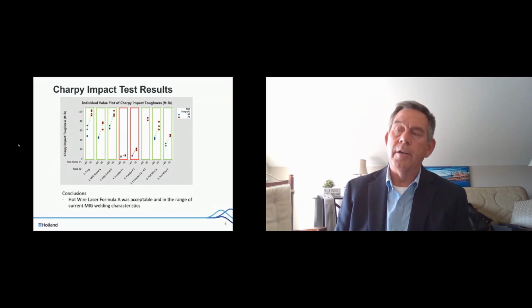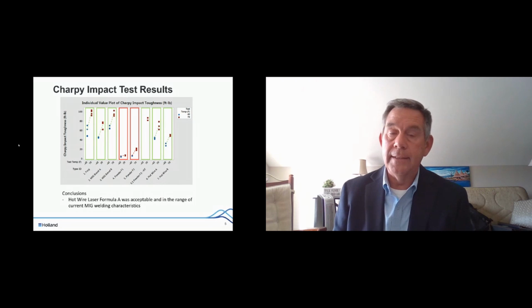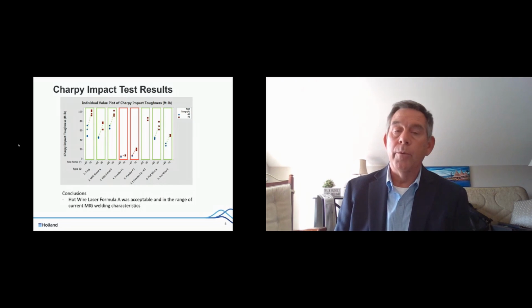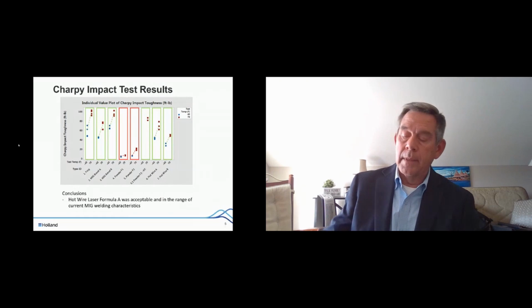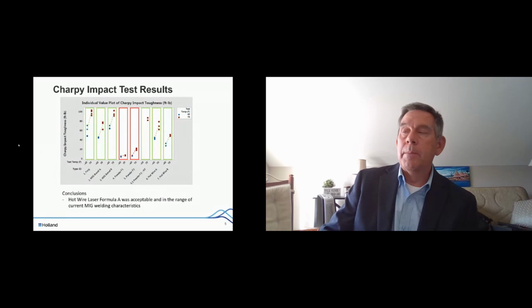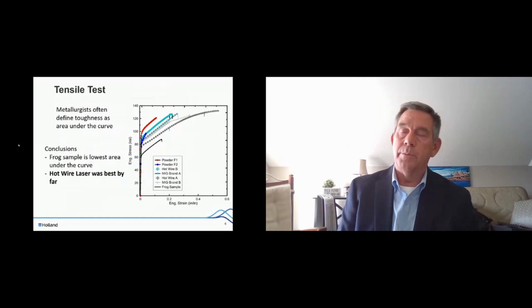The first bar is base frog material, and then the next 2 bars are the MIG welding process with 2 different brands of wire. In the middle there, the red bars indicate our initial testing that produced very poor results. So then we did further research and developed the technique so that, as you can see in the last 2 bars on the right, the results are very comparable now to the MIG welding process. And in fact, our preference for welding is the brand A formulation, because it does have higher impact resistance and is less brittle.